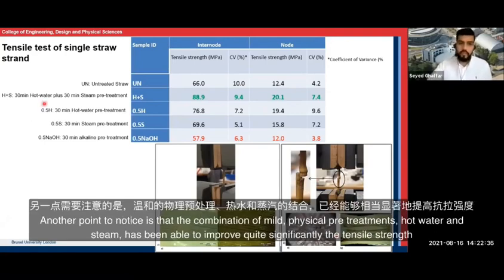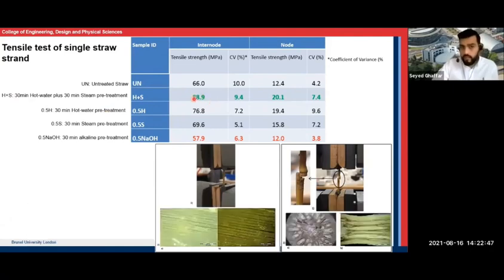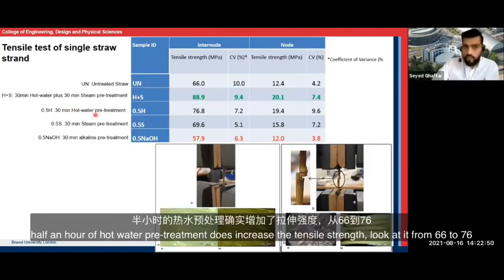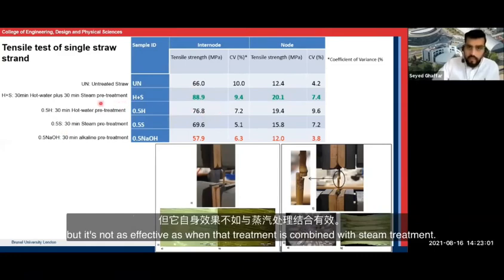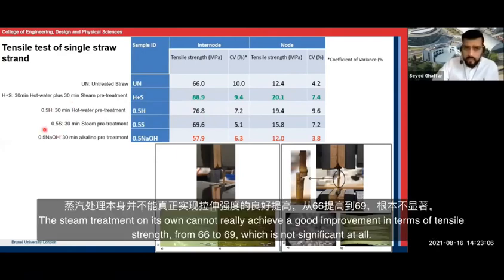Another point to notice here is that the combination of mild physical pretreatments, hot water and steam, has been able to improve quite significantly the tensile strength. The hot water on its own, so half an hour of hot water pretreatment, does increase the tensile strength. We look at it from 66 to 76, but it's not as effective as when that treatment is combined with steam treatment. The steam treatment on its own cannot really achieve a good improvement in terms of tensile strength, from 66 to 69, which is not significant at all.